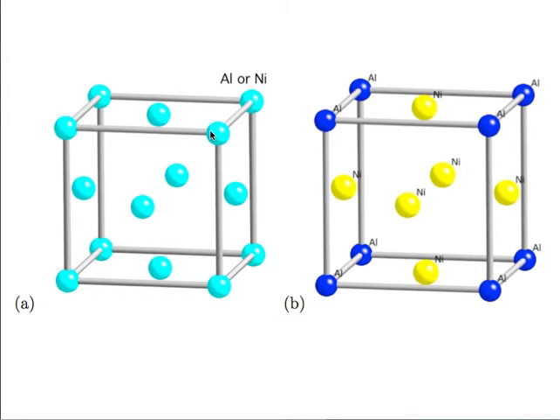Do you recognise this structure? It is a very important structure. The chemical formula is Ni3Al. This is classically known as gamma prime and the matrix is gamma. A nickel-based superalloy in a turbine blade would typically contain 70% precipitates of gamma prime and 30% of the matrix - a huge amount of precipitation hardening.